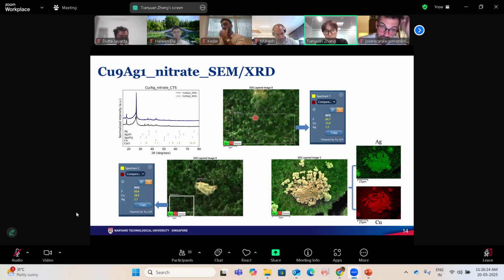And we also did SEM and EDX here. You can see these two pictures. Even in the background, the copper and silver ratio looks good. It remains at 9:1, same as we added before. So it shows that the copper and the silver mixed very well in this sample. And we also found that some parts of the silver and the copper were more likely to combine as a heterostructure, as the pictures show here.